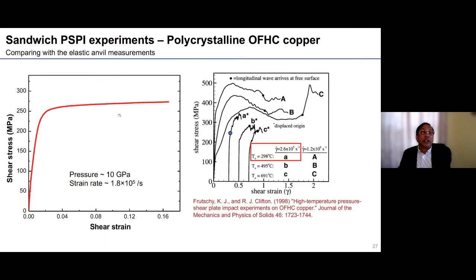Now, so we can obtain from the model. By fitting these experiments, we can obtain the shear stress as a function of the shear strain. This is shown for the 10 GPa, what the model tells us, and the strain rate here is about 2 times 10 to the power 5. And we want to have a sanity check of whether we are getting the right numbers.